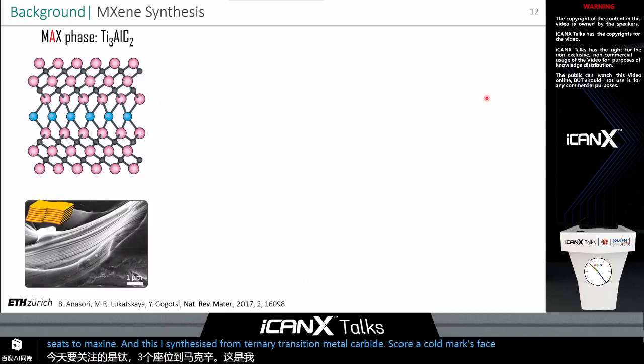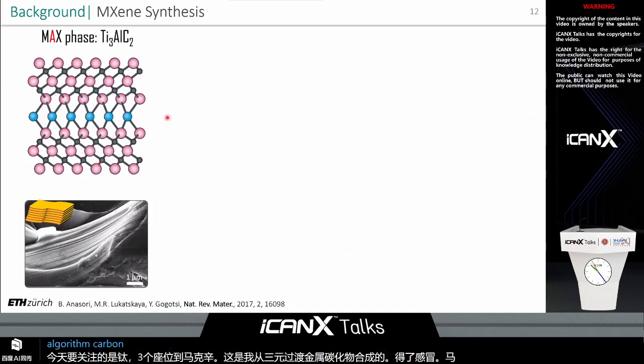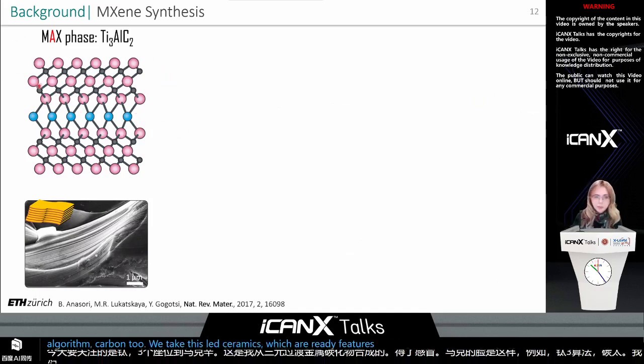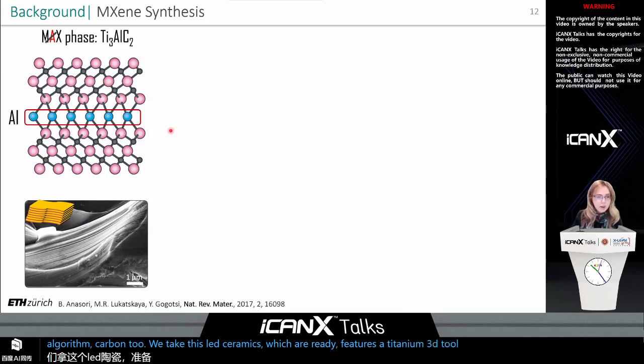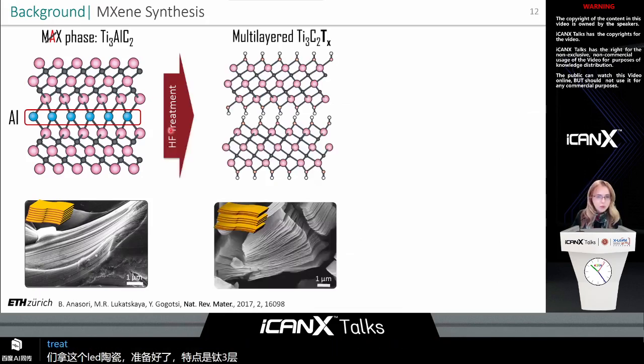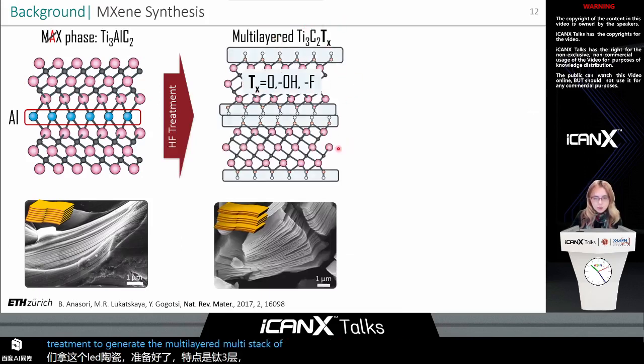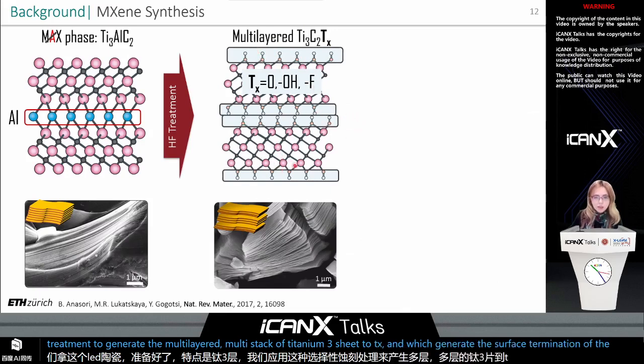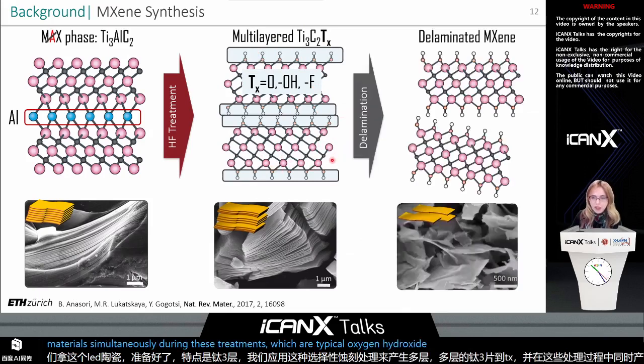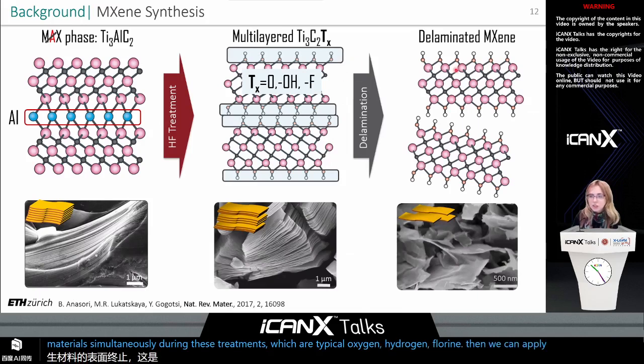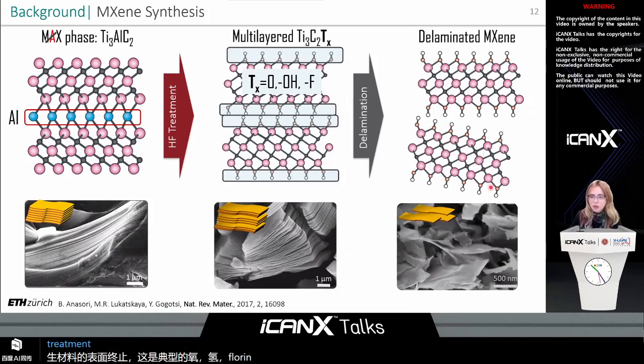So for example, titanium 3 aluminum carbon 2. We take this layered ceramic, which already features the titanium 3C2 layer, and we apply a selective etching treatment to generate a multilayered stack of titanium 3C2Tx, and we generate the surface termination of the material simultaneously during these treatments, which are typically oxygen, hydroxyl, and fluorine. Then we can apply a delamination treatment to generate single flakes of these 2-dimensional materials.